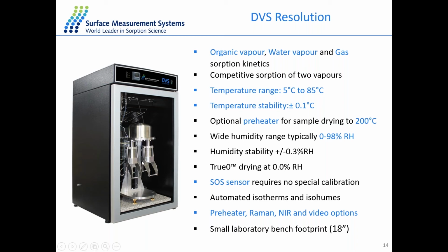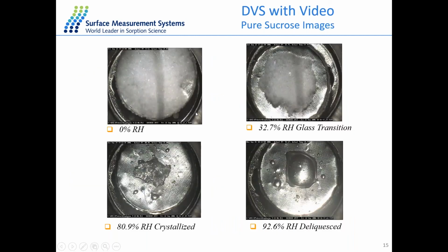We can also combine the DVS system with other accessories, for example a camera, also at this location, to take sample images at different humidity along with DVS data. For example, here with a sucrose sample, at dry condition the image shows a powder form, and then it goes through the glass transition, crystallization at a higher point, and also deliquescence, going to liquid form at high humidity. So this setup, just with the video camera and the DVS, gives us a good idea about how the sample will change in structure, nature, or color along with the DVS data.